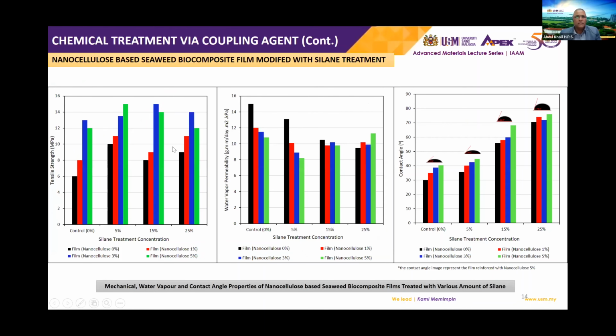The graph explains the result of the surface treatments. The seaweed biocomposites reinforced with various amount of nanocellulose, 1, 3, and 5%, and treated under different concentration of silane, 5, 15, and 25%. The tensile strength, water vapor permeability, and the contact angles of the biocomposites were enhanced as the silane concentration increased up to 25%. The silane treatment helped to enhance the properties of the seaweed nanocellulose film by bridging the silane network with OH groups of the seaweed and nanocellulose. The bonding improved the properties of the film, such as mechanical, physical, and etc.